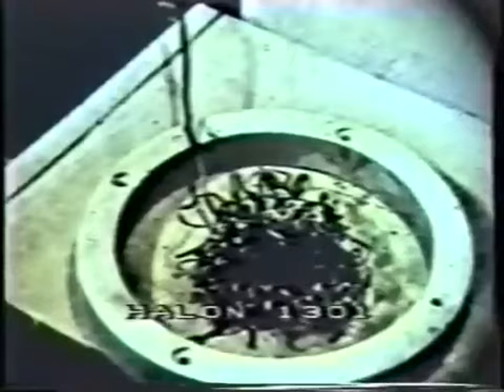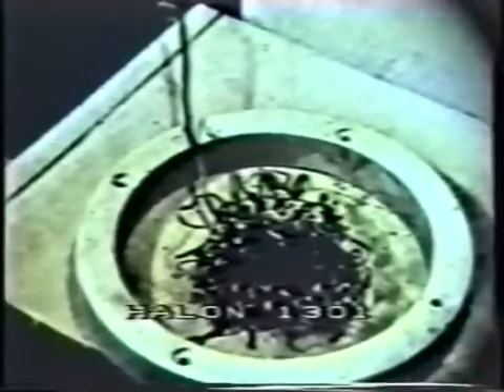As we apply the bonnet here, you notice the reaction that you get. The bromotrifluoromethane is actually decomposed into hydrofluoric and hydrobromic acid at around 2000 centigrade. The fire burned through the thermocouple, which cut out at 1800 centigrade. Estimated we went to in excess of 2000 centigrade. And so